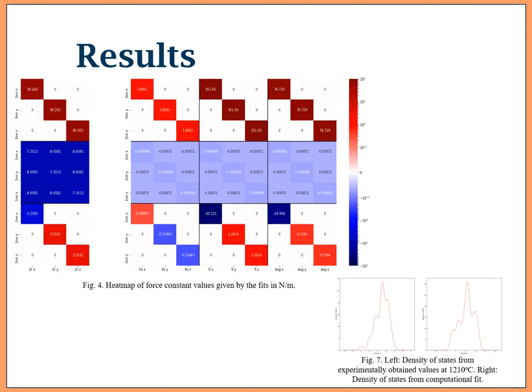First we have a heat map of the results for up to second nearest neighbors, and second we have a comparison of density of states curves between our fitted values and experimental results. Both plots seem pretty similar, with only a few differences in scale.